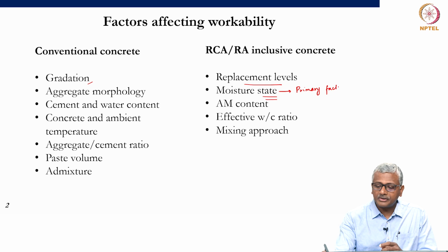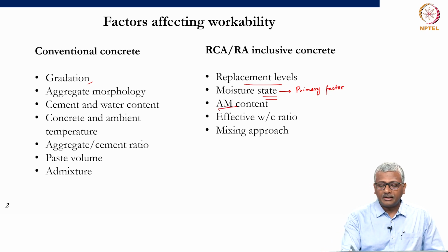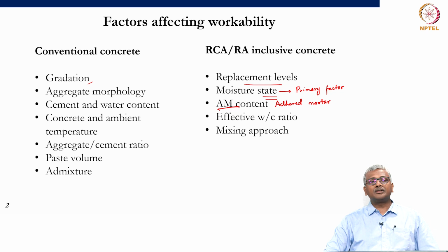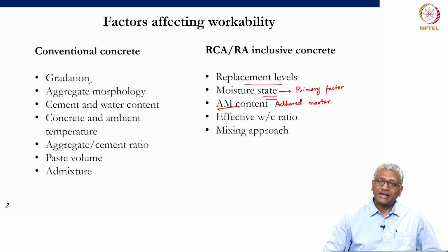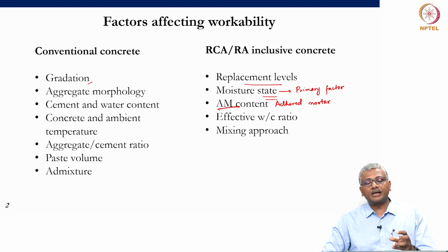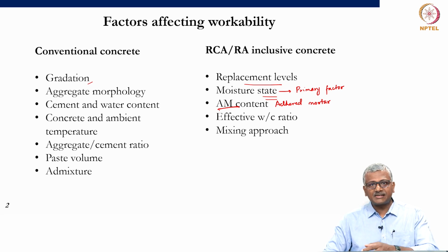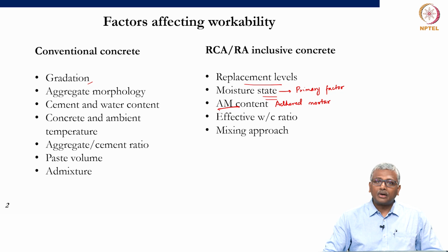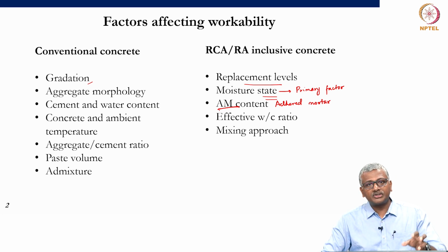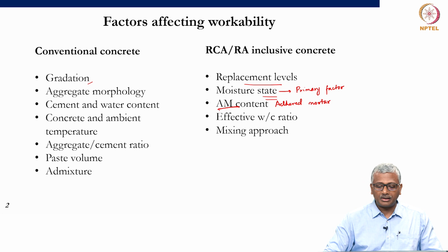factor, because as we discussed earlier, there is adhered mortar which sticks to the surface of the recycled concrete aggregates. The adhered mortar is definitely going to be a lot more porous as compared to your natural aggregate, and because of this adhered mortar, there is a tendency for the recycled aggregate to absorb a lot of moisture. We'll see some examples later on, and you'll see that the absorption of moisture by the recycled aggregates is the primary concern with respect to either achieving workability or not achieving workability. We'll talk about that in more detail later.